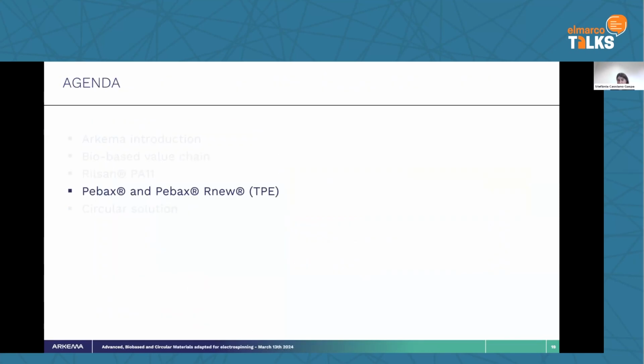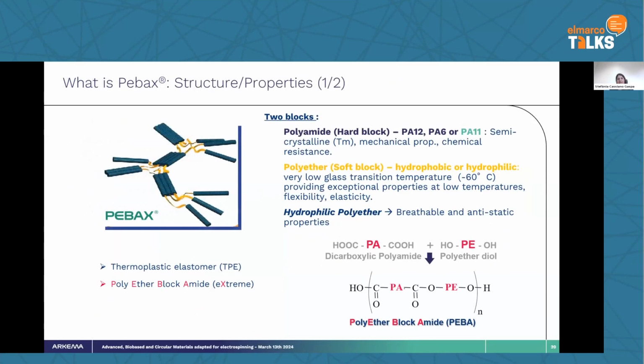Now, very shortly about Pebax. So what is Pebax? It's a thermoplastic elastomer, okay? It's made of 2 blocks. We have a rigid block made of polyamide. This rigid block can be either polyamide 12, polyamide 6, and of course, polyamide 11. When it's based on polyamide 11, it's our Pebax Rnew product range. The polyamide block provides chemical resistance and good mechanical properties to our Pebax.